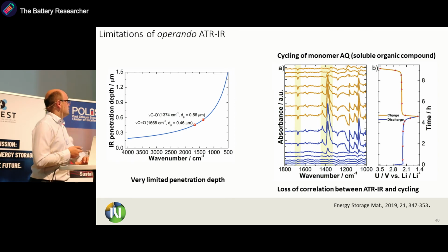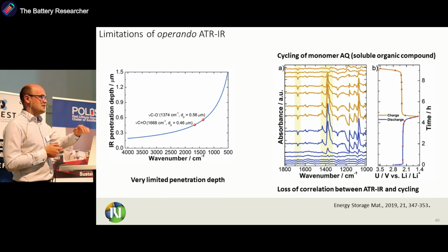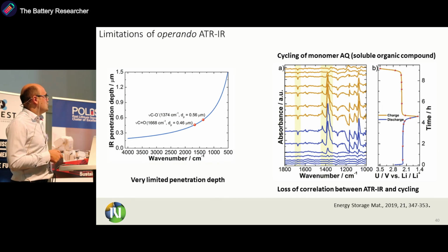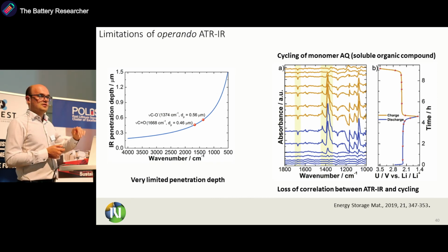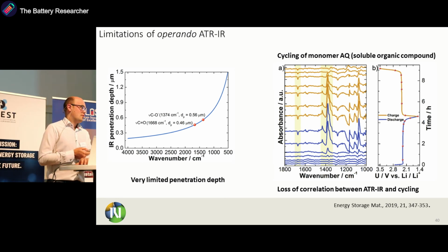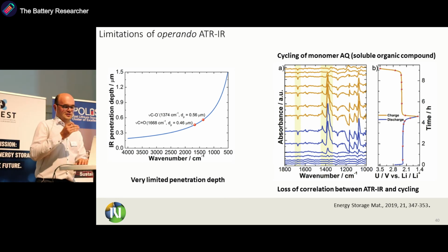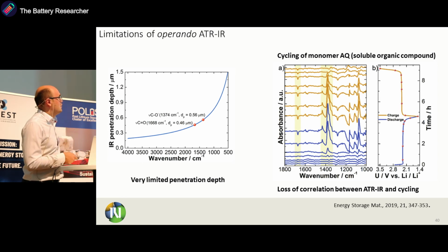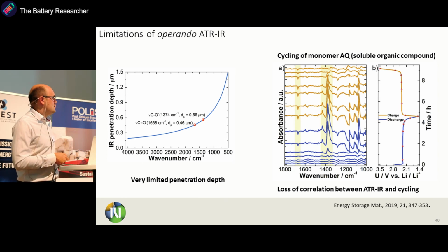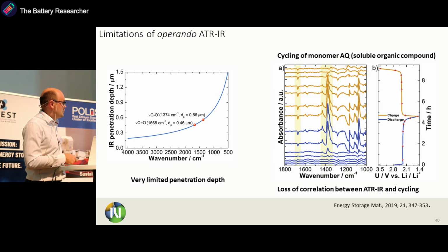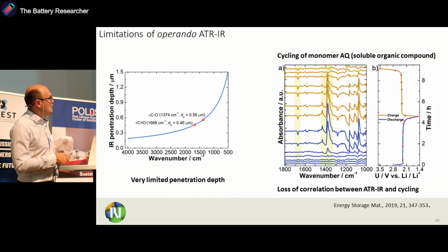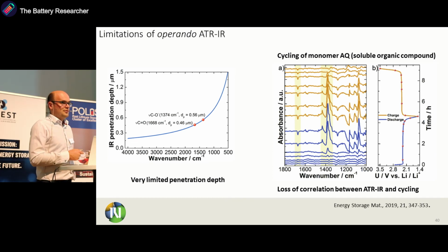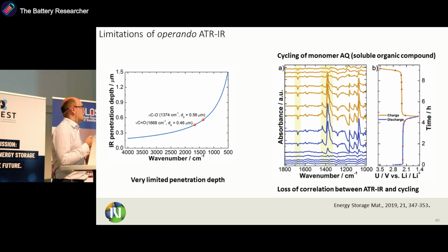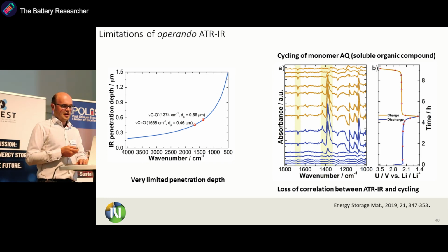Of course, there are also limitations to this method. Like I said, we are probing from the backside, and the penetration depth is quite low. So basically, we just see few micrometers inside the cathode, and this can become a problem when reaction is not homogeneous along the thickness of the electrode. And this is the case when you have anthraquinone soluble organic compound. You can see when you take a look at this spectra here, where you expect a lot of change in the plateau, you don't see anything, and you see something only towards the end. So this means that because anthraquinone is soluble, you lose the connection between the electrochemical activity and the information that you get from the infrared spectra.